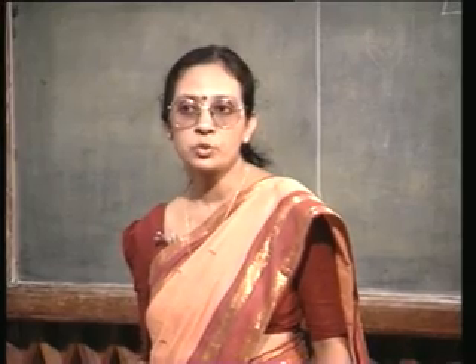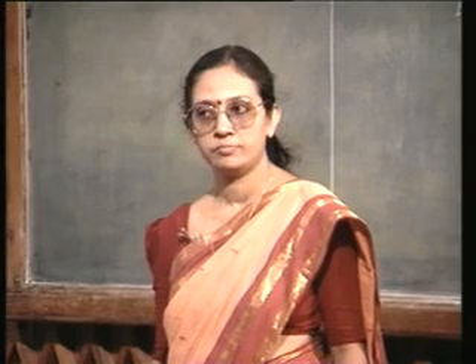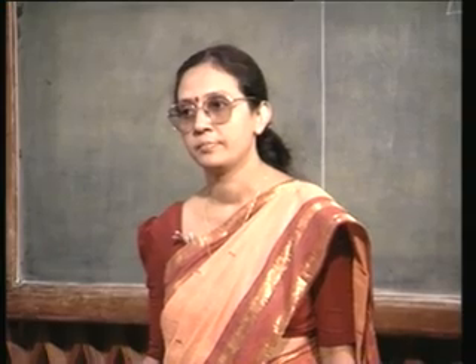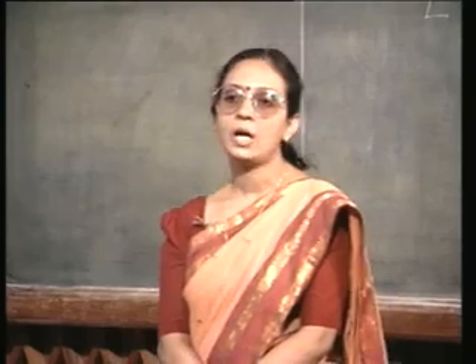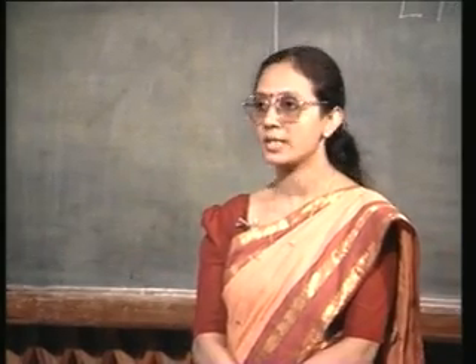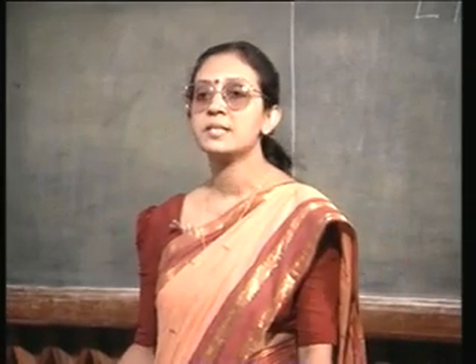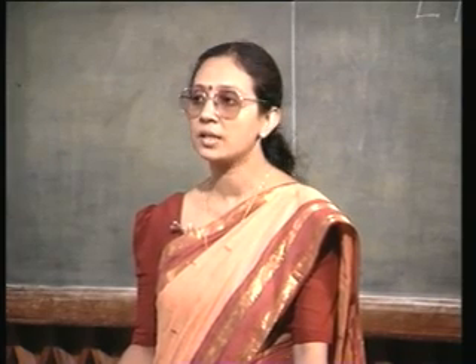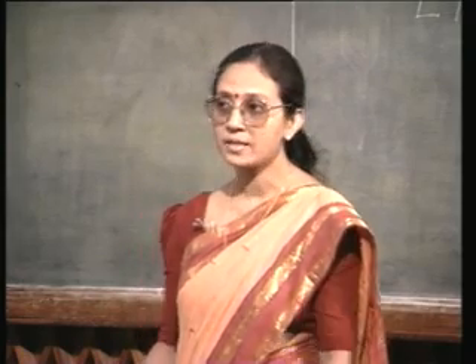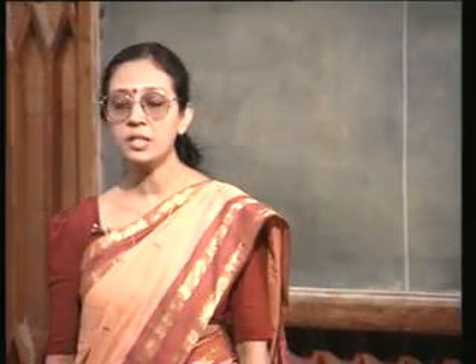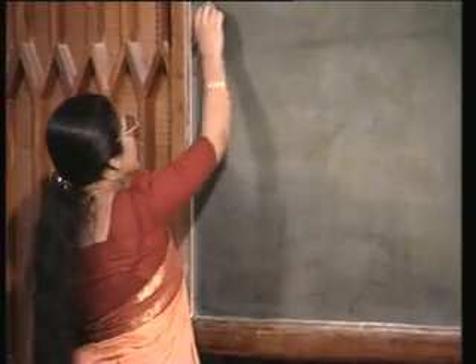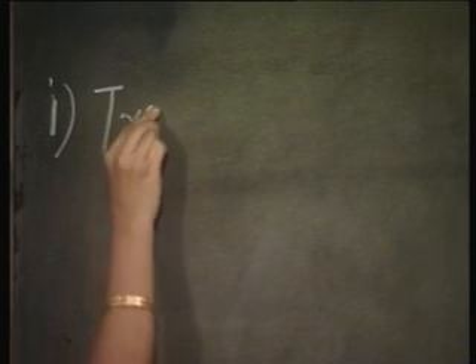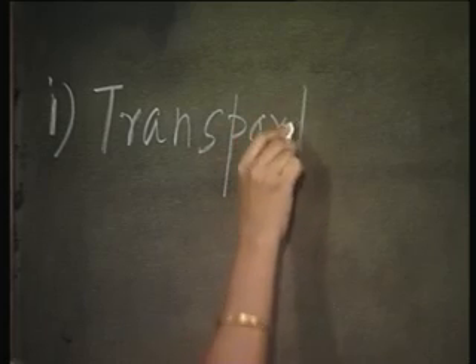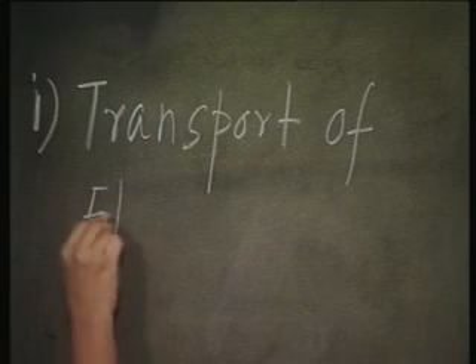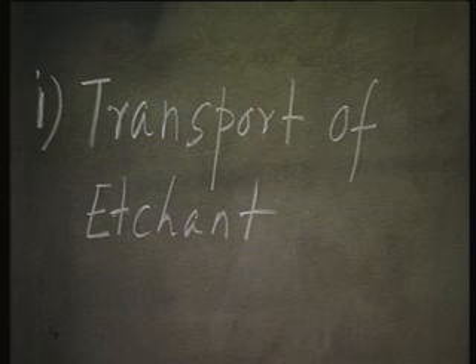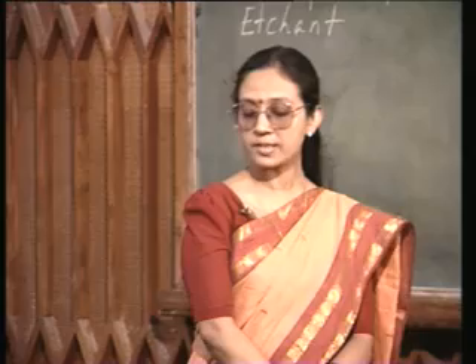So, you put your substrate material into the etchant solution, and what are the things that are going to happen inside? First of all, you have some etchant material in the solution, for example hydrofluoric acid in your HF solution. You want this hydrofluoric acid to be made available to the silicon dioxide with which it is going to react, right. So, that is the first step, transport of the etchant material to the surface of the material that is to be etched. Transport of etchant from the solution to the surface that is to be etched.